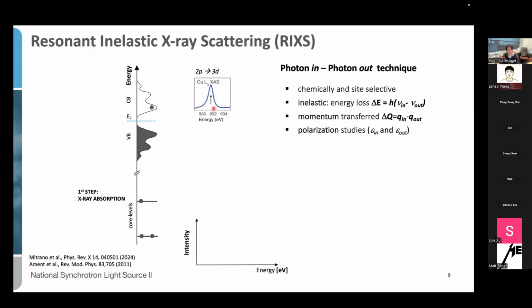Once the system relaxes back, it can do so in various ways. Among them, we can now consider an electron from the valence band that goes back to fill the empty core state. And after this process, we have then an emission of an X-ray. By analyzing in energy the emitted X-rays, and since we know, because we tune the incoming energy, we are basically finding out the energy loss that we have transferred to our material, to our system. And this energy loss corresponds actually to the energy needed to create an excitation in our system. And this is the information that we record in our RIXS spectrum.